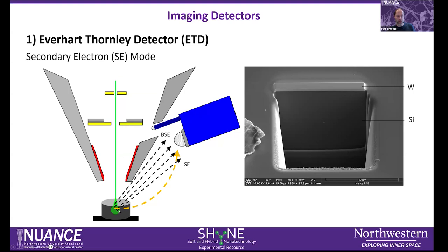This detector can be used in secondary electron mode. You have a primary electron beam, and this is the pole piece. You generate a variety of signals, and if you apply a positive bias to the detector, you can attract lower energy secondary electrons generated from your sample, and visualize, for example, this cross-section in silicon - a relatively large area cross-section where we've deposited some tungsten on top of our region of interest to protect it from ion beam penetration.